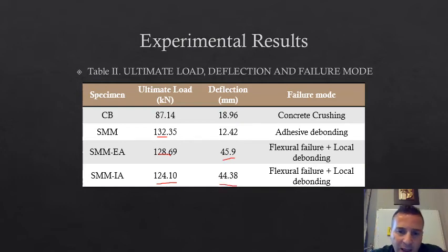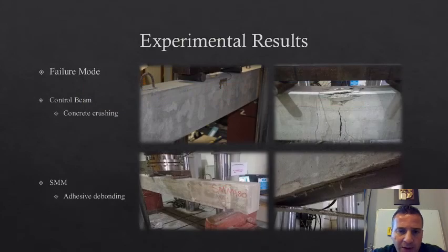This means that anchoring the ends or intermediate anchors of the sheets to the concrete will enhance the ductility of the specimen. Not only that, you are going to change the failure mode from brittle debonding to flexural failure by yielding of the steel reinforcement and concrete crushing, and this will provide a ductile strengthened structure, which is favorable over the brittle strengthened structure.